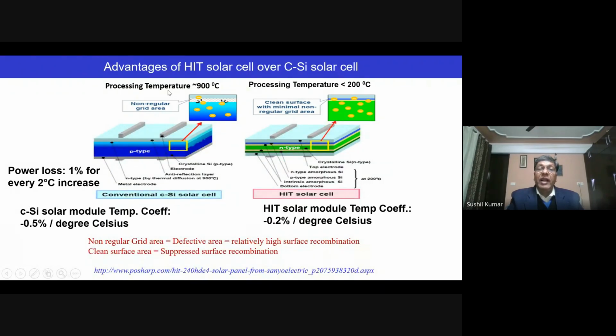The other advantage is that conventional crystalline silicon cells are made at 900 degrees, because you have to go for diffusion of your material to make the PN junction, and for that temperature you need at least 900 degrees Celsius. But here you can grow at less than 200 degrees C. You need a PECVD process like I have shown you. One can grow good quality amorphous silicon at 180 degrees C, even the intrinsic and the doped layers. So this is the advantage here: you have a lower temperature coefficient and a lower temperature for making the cell. So it's an added advantage.